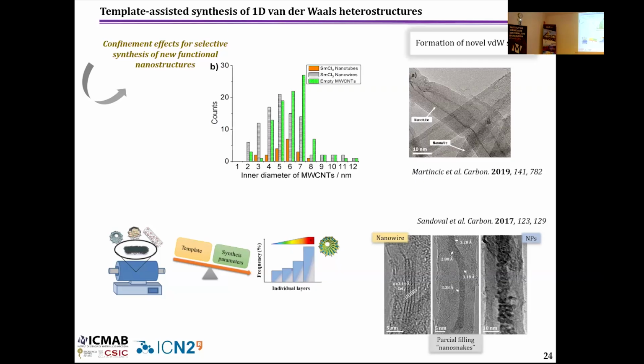So there should be a two-step process, but we haven't filled with oxide. Maybe a good idea would be to fill the nanotubes with metal organic precursors, and make them react inside with high temperature annealing or whatever, and maybe you can get different structures, no? Because it's confined. The only problem is that if you oxidize in air, you can burn the nanotubes. So you should use another protocol to oxidize it because, of course, they are very stable, but above 600 degrees, you burn them. So it's not straightforward. But yes, it could be done.